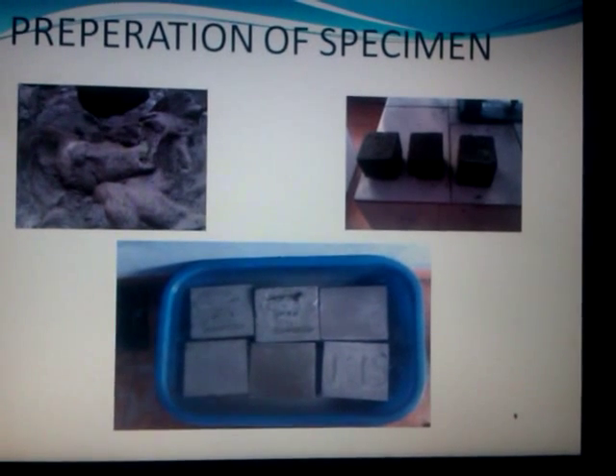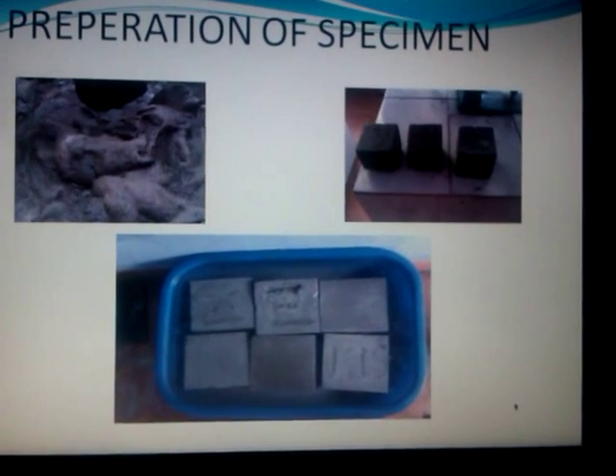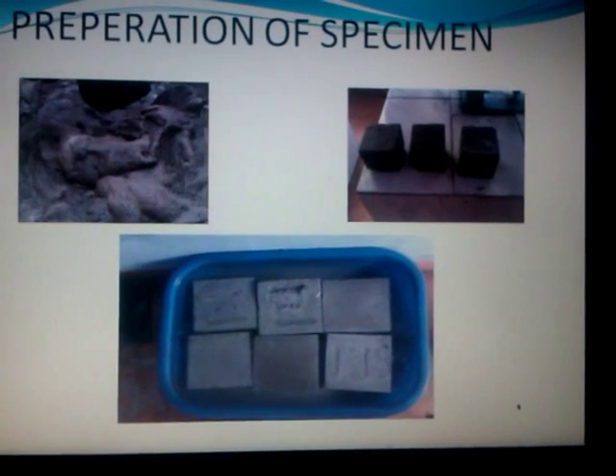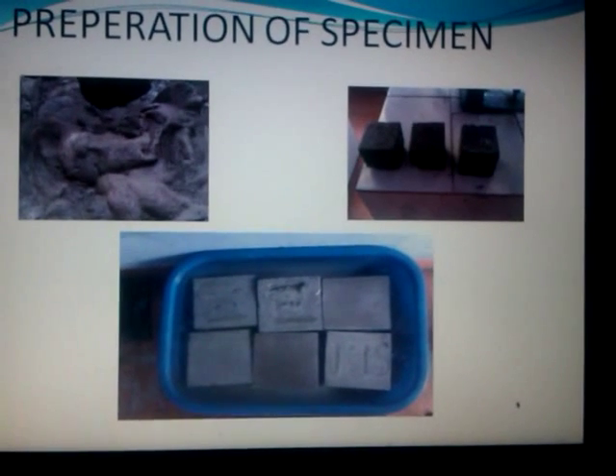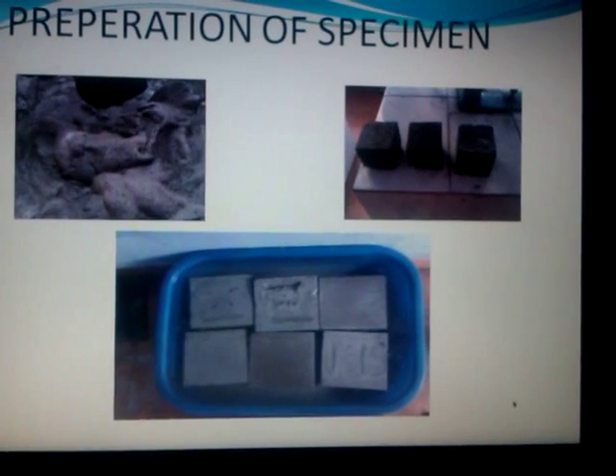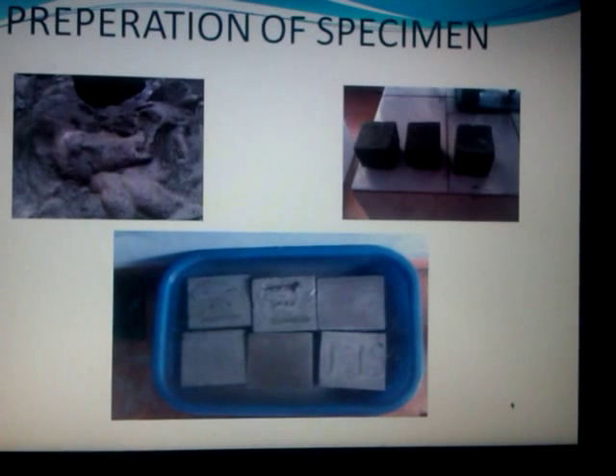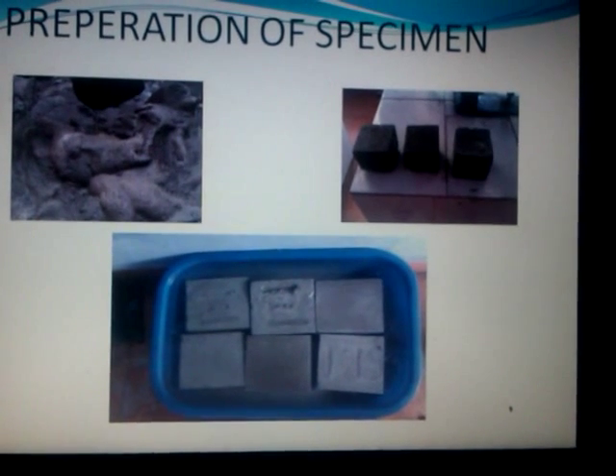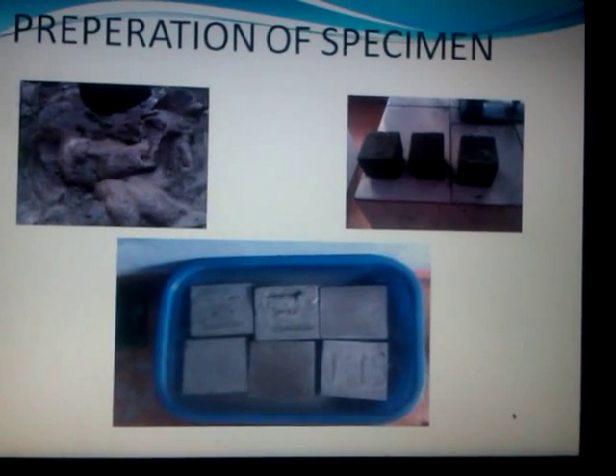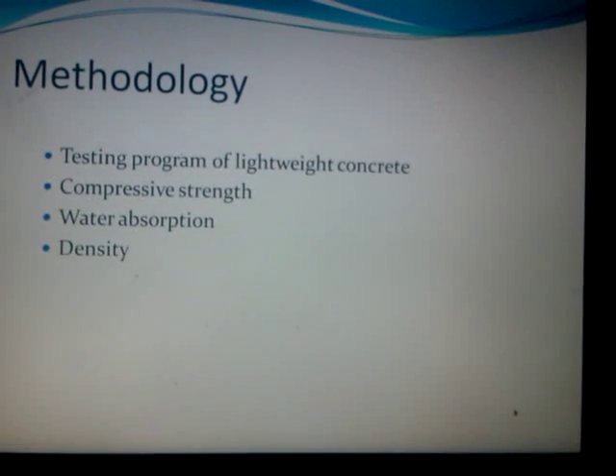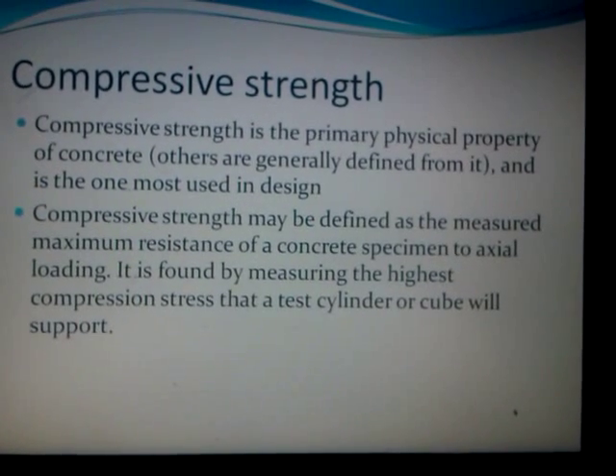These are the preparation steps for the specimen. We have used the pre-foaming method for preparation of lightweight concrete cubes. The cement slurry was mixed into the foam to create the cubes. Two types of curing were performed: 7-day and 28-day curing.